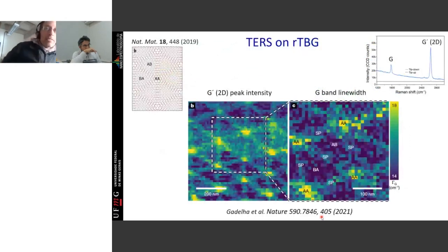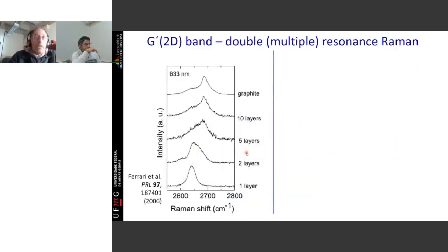Okay, let's go further and see what all sorts of information, physics and science you can obtain by imaging these moire structures, by imaging the structure and looking into all the information that you get from the several peaks in graphene. All right, one is, it has been established in the literature, in a 2006 paper, where a group from Cambridge in England demonstrated that the line shape of a given vibrational mode tells you if you have 1 layer, 2 layers, 5 layers.